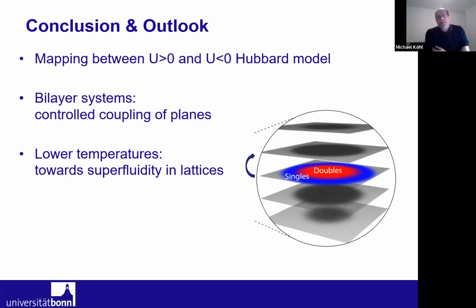In the future, we would, of course, like to see if we can reach lower temperatures and lower entropy states in the lattice. And there, the bilayer system could actually help us. The bilayer system could also allow for a novel way of reaching superfluid phases in the lattice, slightly different from the standard two-dimensional Hubbard approach, because the coupling between the layers gives you additional degrees of freedom that can actually enhance superconducting pairing under certain circumstances. So this is where we would like to head in the future.